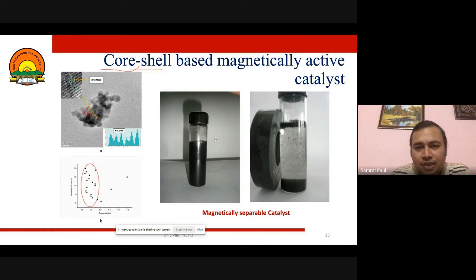And this is one of the carbon based materials that we have also developed for catalyst development. We can see after incorporation of this type of core shell material, the magnetically separable catalyst is immediately separated from the biofuel that has been generated. So a core shell material, magnetically separable, makes it very easy to separate the catalyst and to reuse the catalyst again. This is one of the works that we are trying to patent, though we have not filed it, and that's why I'm not giving much detail. We are working to develop it further.